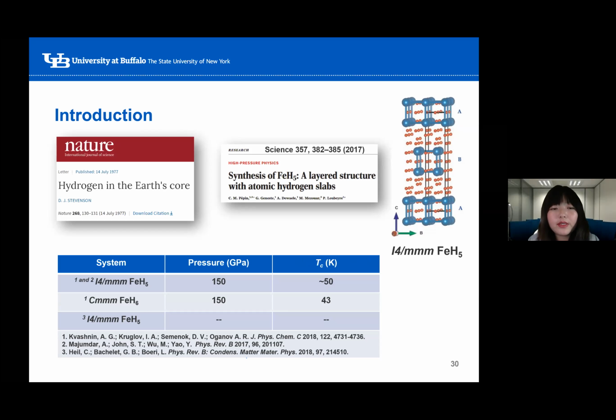Theoretical studies predicted a Tc of about 50 Kelvin and a Tc of 43 Kelvin at 150 GPa for FeH5 and FeH6. However, this wasn't observed in the experiment, and another later theoretical study disagreed. So this discrepancy motivated us to carry out our own search for FeH5 to 8 in the pressure range between 150 and 300 GPa.